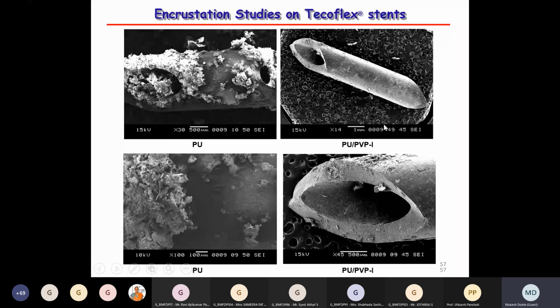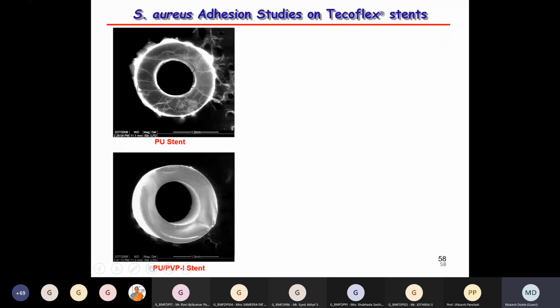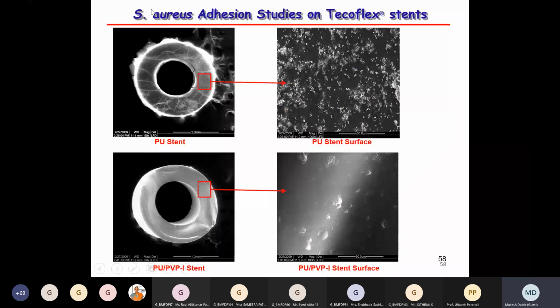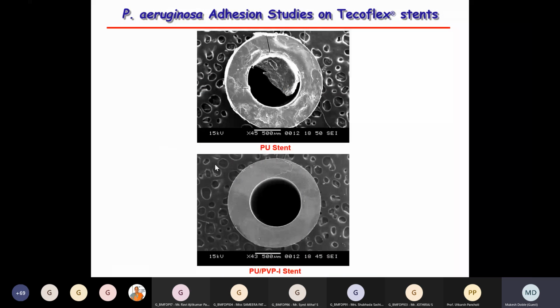Then, because the salts don't encrust, we can also look at how bacteria get attached, like Staphylococcus aureus. As you can see here, there is a lot of bacterial biofilm, but once we modify the surface, you can see on the bottom side there is no bacterial adhesion. This is one bacteria; this is another bacteria, Pseudomonas aeruginosa. Again, you can see a very clean surface here, absolutely no bacterial biofilm formed. So this modification seems to work very well. We are able to prevent both salt incrustation and bacterial biofilm formation.